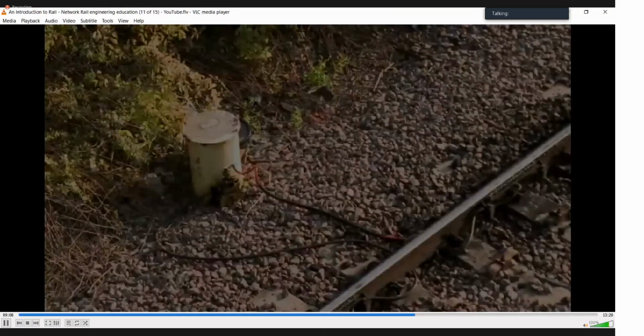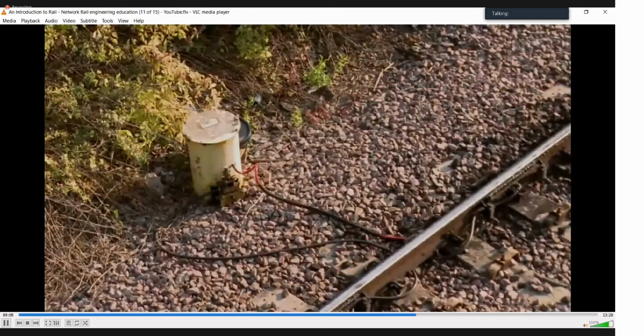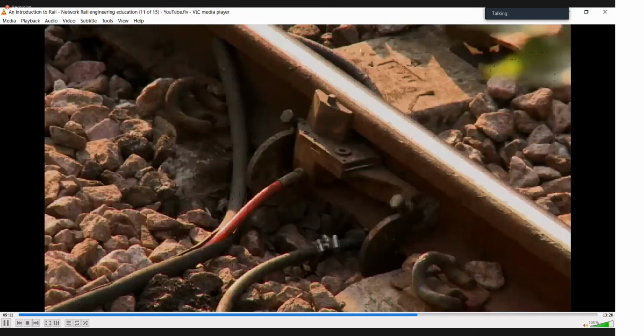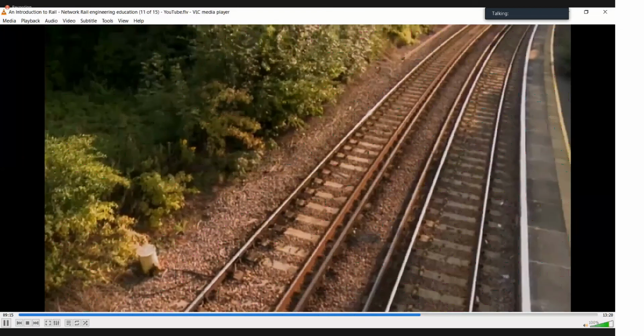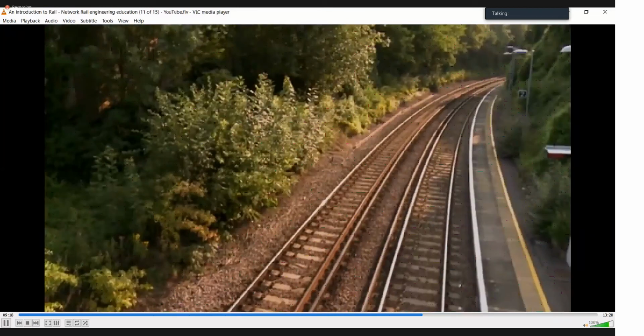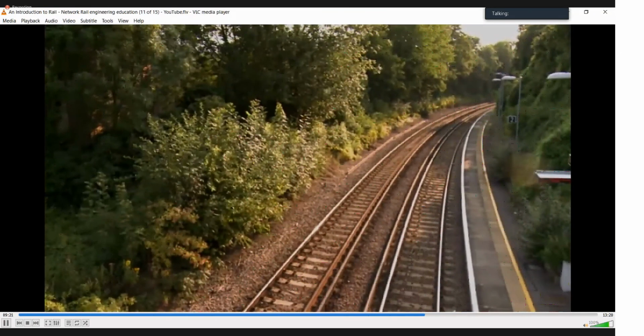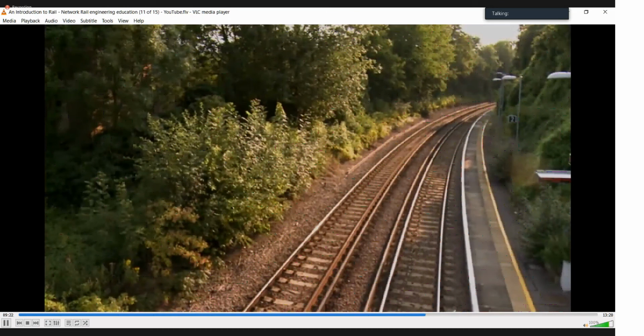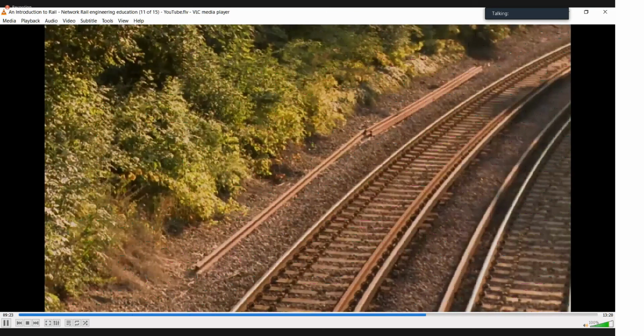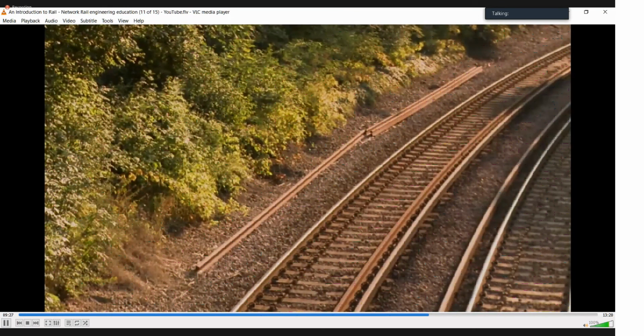We use lubrication to minimize rail wear. Track-based lubrication equipment deposits a small bead of grease onto the wheel, which is then carried around the outside bend of a curve. Lubrication is used on most tight curves on the network to reduce rail wear and the premature replacement of the rail.